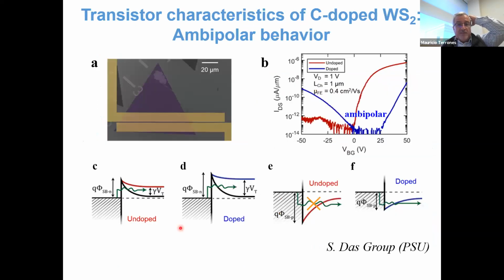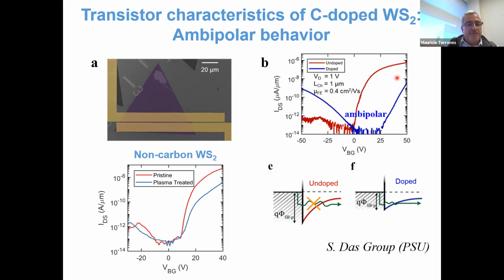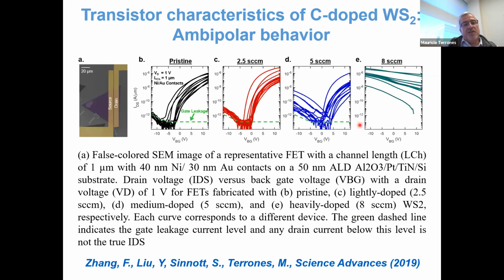And again, this is very interesting because with Saptarshi's group, we first found that if we doped with carbon, at some point we could see an ambipolar behavior. Again, remember the tungsten disulfide is N-type. And if we just do the plasma treatment without methane, nothing happens. You don't see this ambipolar behavior. So this is related to the introduction of carbon. So can we introduce carbon in different concentrations? And the answer is yes.